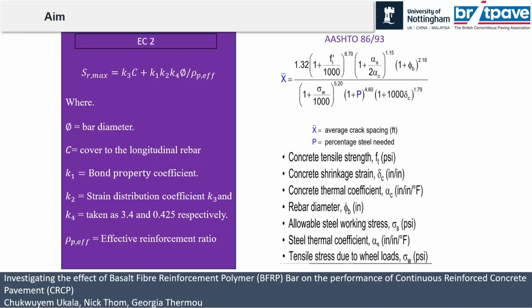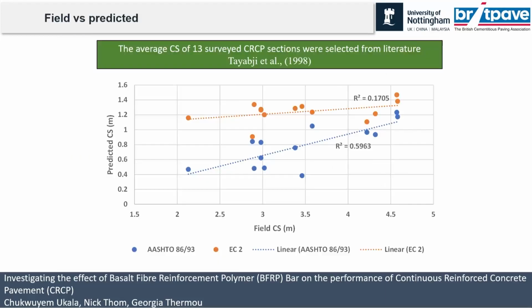So we selected two popular models. We used the EC2 and also the AASHTO 93 model to see what happens in the steel member when it is subjected to direct tension. And what we did was take two models that have similar kinds of parameters, such as the crack spacing, the cover, the reinforcement ratio, the bar size, things like the CTE, that's the coefficient of thermal expansion of the steel and that of the concrete, just to see what happened. Other additional models exist, but for the scope of our work, we used these two to try and explain what happens within the steel CRCP in terms of the crack spacing.